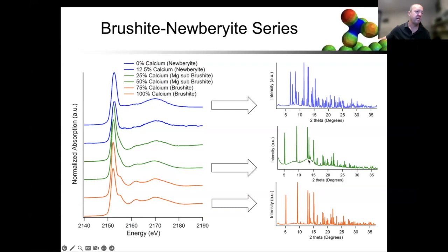The X-ray diffraction suggests that there's a fair amount of amorphous material in here, but that whole system is dominated by exactly the same scattering peaks. So the green spectra here in the middle are the same phase as the orange spectra. They're just much less crystalline.